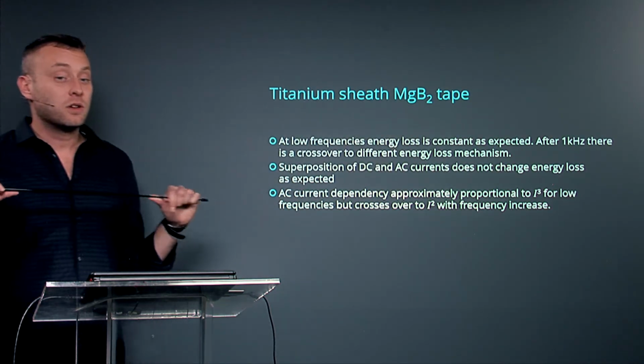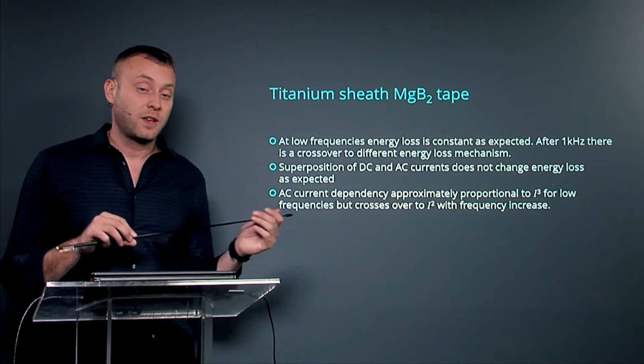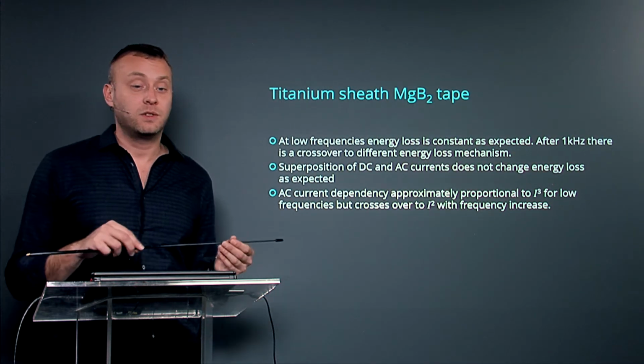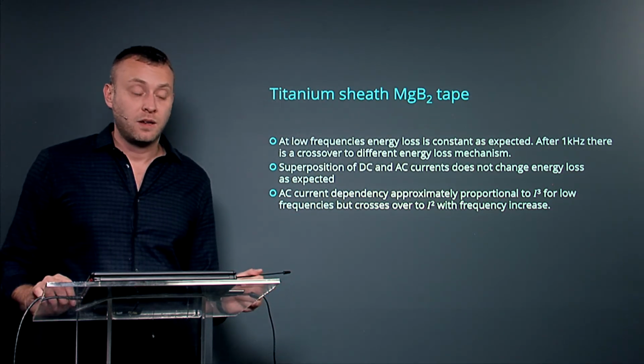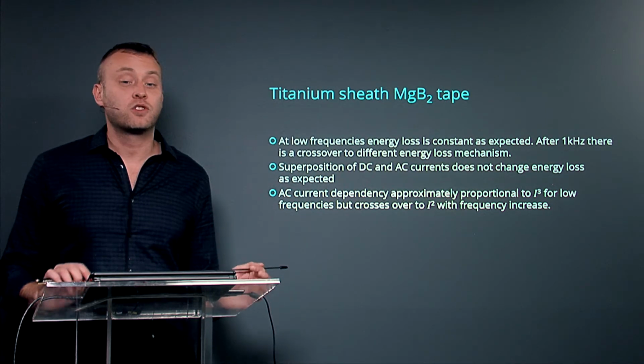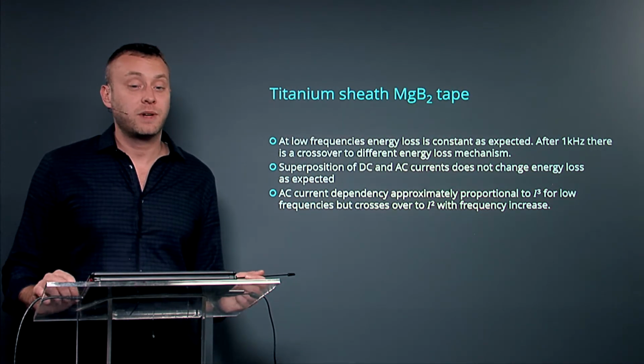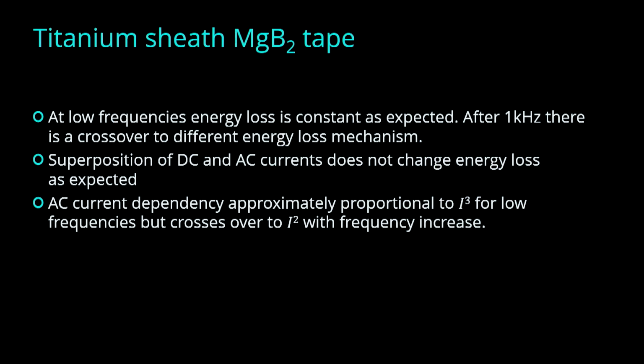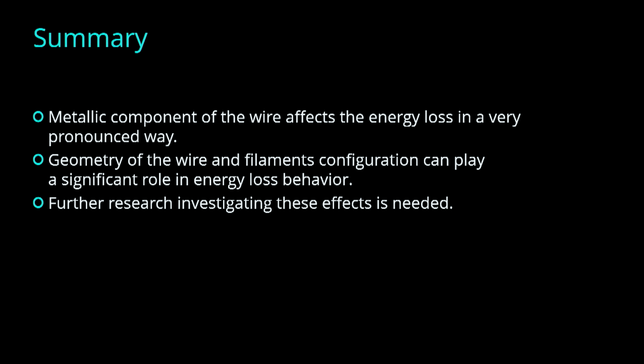So we see the energy loss for titanium is constant as expected. After around 1 kilohertz, there is a crossover to a different energy loss mechanism. Superposition of DC and AC current does not change energy loss as expected, and the AC current dependency is approximately proportional to I cubic for low frequency, but crosses over to I square with the frequency increase. As I said, the metallic component of the wire might affect energy loss in a very pronounced way, as well as the geometry of the wire, the number of filaments and the configuration of the wire itself can play a significant role in energy loss.